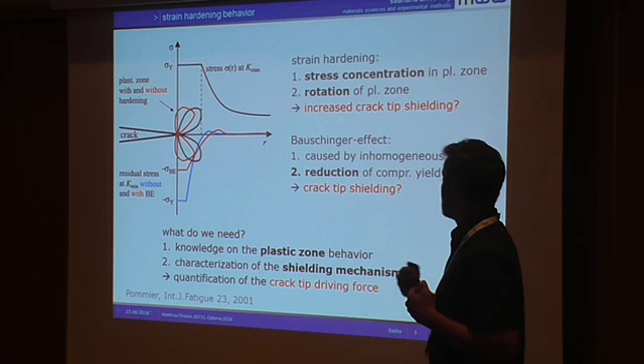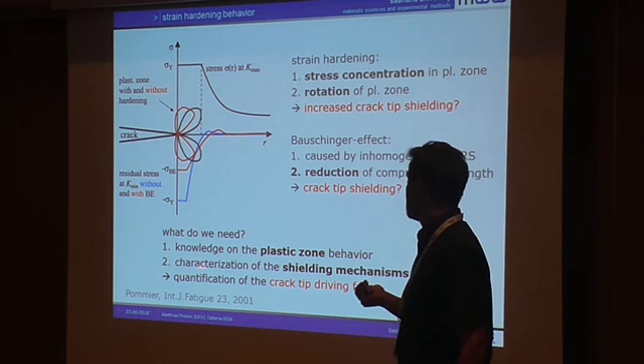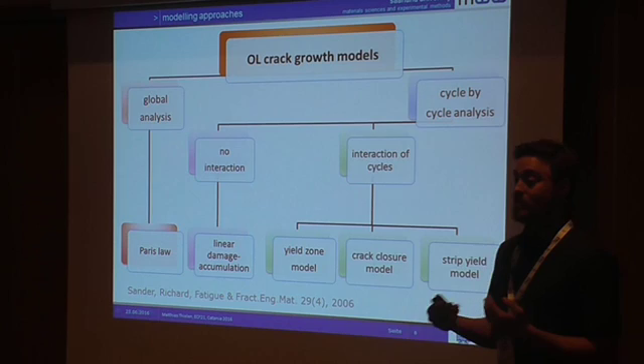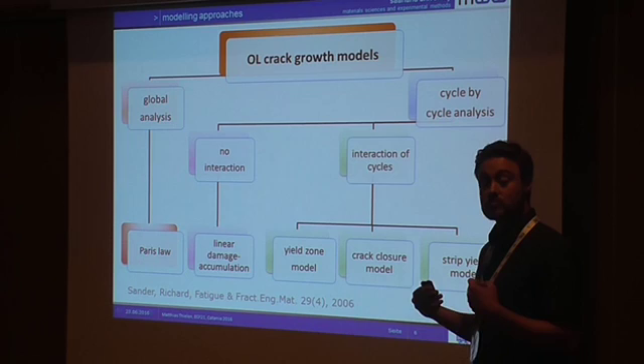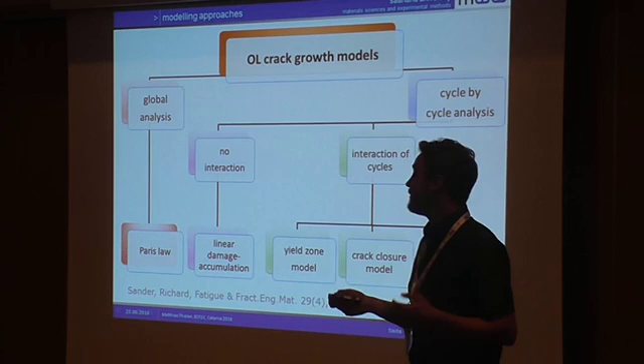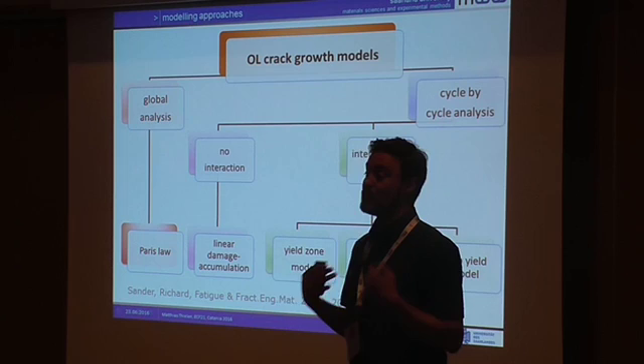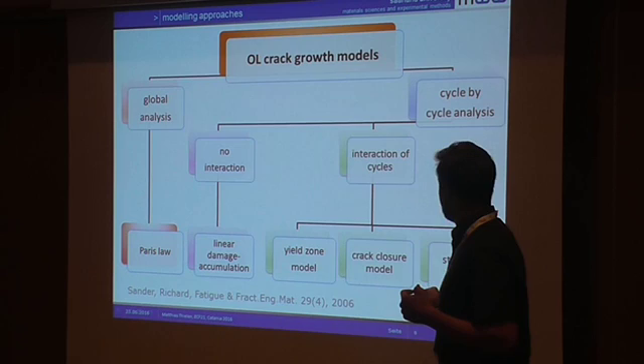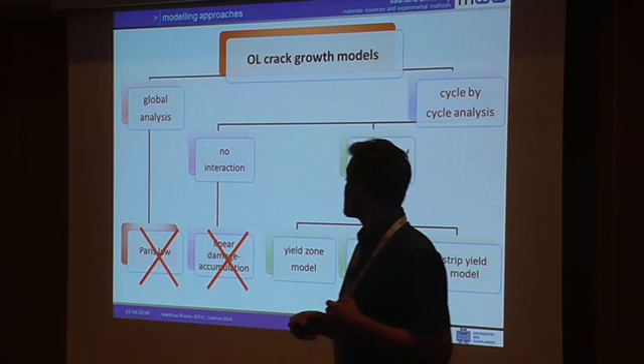If you want to characterize this experimentally, you need to know the behavior of the plastic zone, and then characterize the hardening and the crack driving force. The Paris law fails for this, but there are other approaches to describe overload behavior. You can divide approaches into global analysis and cycle-by-cycle analysis. The Paris law is the global analysis; the cycle-by-cycle analysis without interaction — linear damage accumulation — works if fatigue is dominated by crack initiation, but if you have history effects and crack growth, linear damage accumulation fails. These approaches won't help us describe overload crack growth behavior.